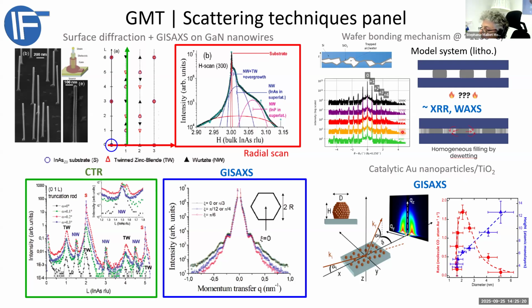Another thing we can do is to illuminate this model system where you have such an electronic density feature. So this is, I guess, air or water. This is silicon oxide, and this is silicon. And then if you do the Fourier transform, or some scattering experiment, you should obtain this kind of scattering curve, intensity as a function of the angle. Around the Bragg peak, which corresponds to the periodicity of the constructive interferences between these layers, you can have access to the shape of your elements.